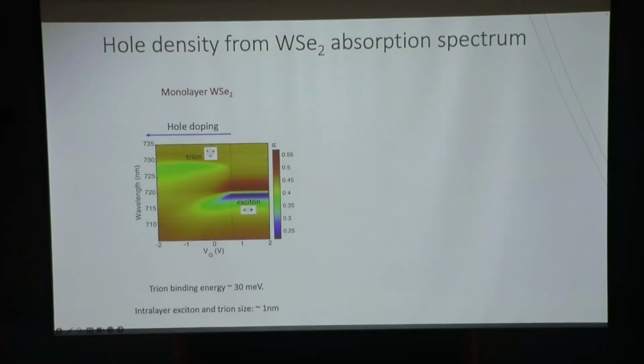Okay, so once you have this kind of heterostructure, and you dope electrons and holes into the system, how do you know what's happening? We can make use of optical spectroscopy, which has already been well established for these monolayer semiconductors. They have very strong Coulomb interactions, so they form tightly bound optical excitons inside the layer. Looking at reflection as a function of wavelength on the vertical axis and the gate voltage on the horizontal axis, over here the system is undoped. So you have a regular semiconductor, and you can see a very strong response that corresponds to an exciton transition in this monolayer. This is an optically excited intralayer exciton, an electron and hole sitting in the same layer.